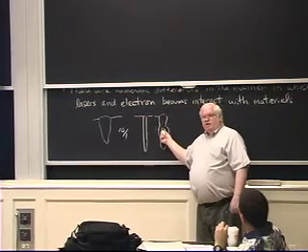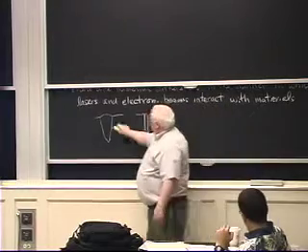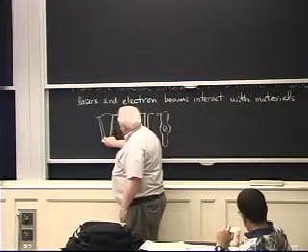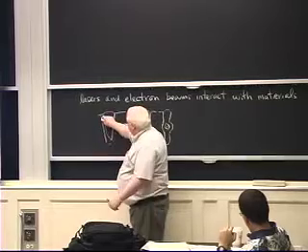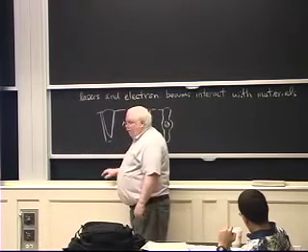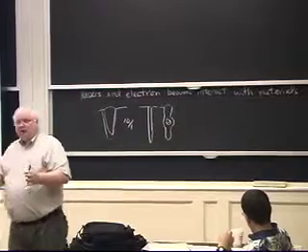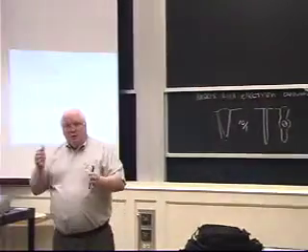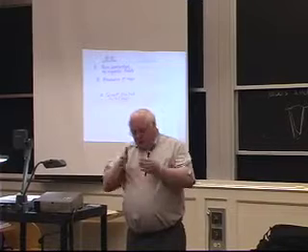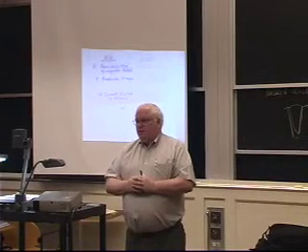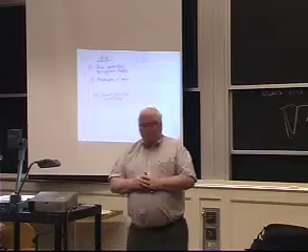All the shrinkage is going to be trapped right in there. Common problem. You need walls that have a slight taper to them so that it solidifies like that, not walls that are straight. So it turns out the focus of that electron beam and the optics, the F number if you're a camera bug, but there's an F number to the optics of the electron beam, just like there is for a camera. That F number has to be a big F number so that you have nice parallel sized beams.